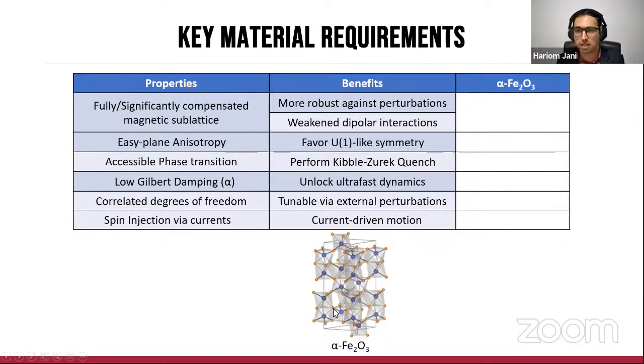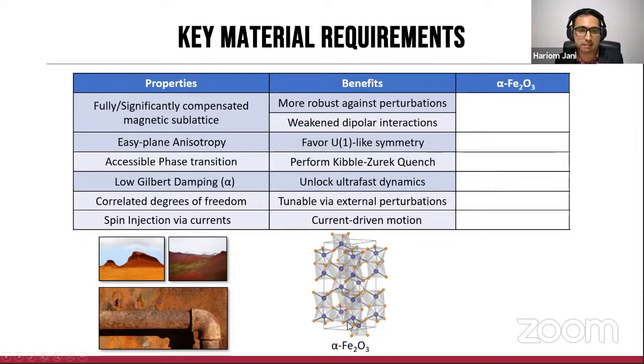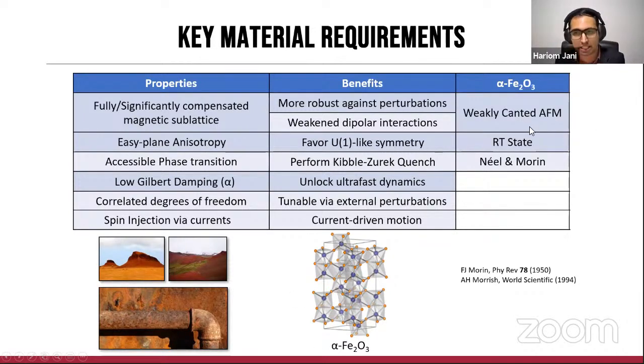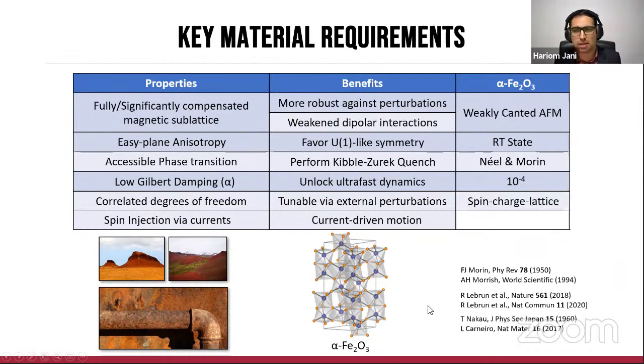This is because it consists of weakly canted antiferromagnetism, and it has a room temperature state exhibiting effectively U(1) symmetry. It is not exactly U(1) because it actually has a sixfold structure, but because the basal anisotropy is really weak, we can effectively call it U(1)-like. It has access to both Néel and Morin transitions. There is a very nice body of work done in Mainz, which shows that the Gilbert damping in the system is ultra low, making it really promising for ultrafast dynamics.